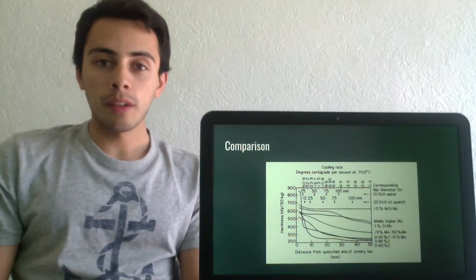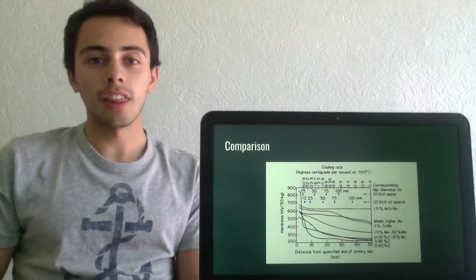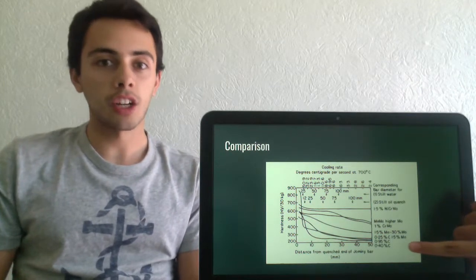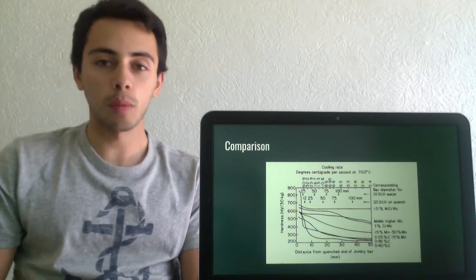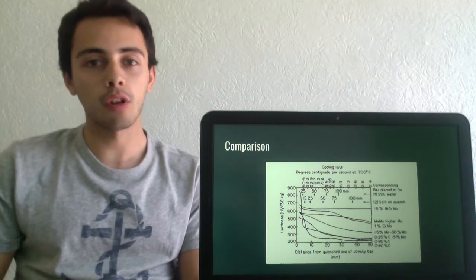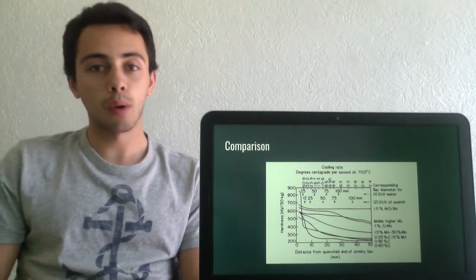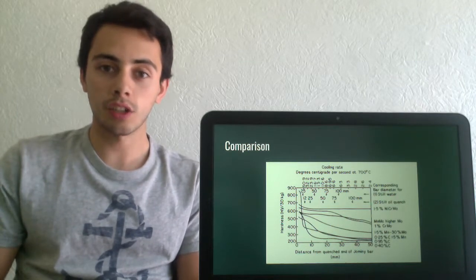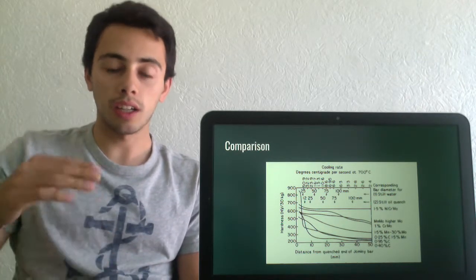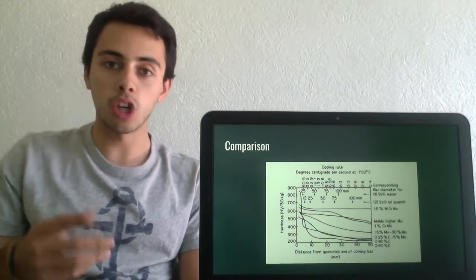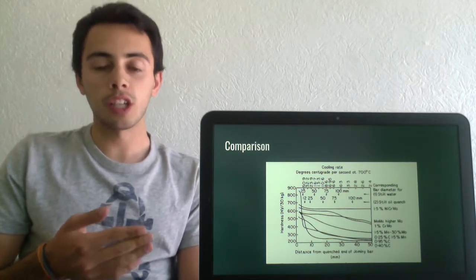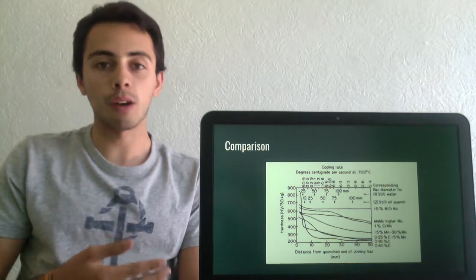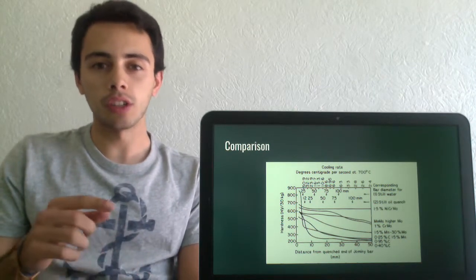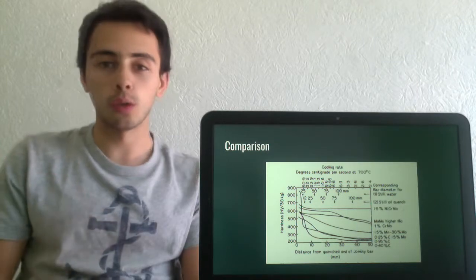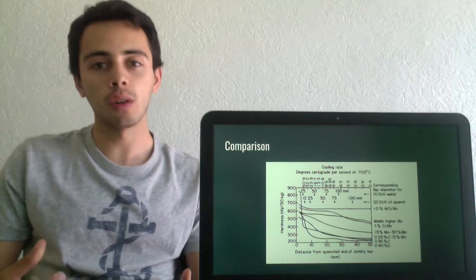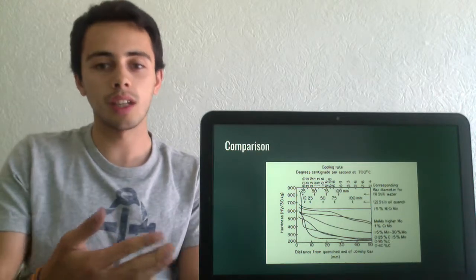This graph shows different Jominy curves for different types of steels, and these last ones show the ones for plain carbon steel with 0.4% carbon and 0.95% carbon. Therefore, our steel 1018, which is 0.18% carbon, will be similar to this curve, and we can see that it starts high and immediately drops down, which is similar to the experimental curve that we found. In our experimental curve, there were several peaks later on, but these were just due to experimental errors. But in general, the curve shows the tendency we see in this curve.